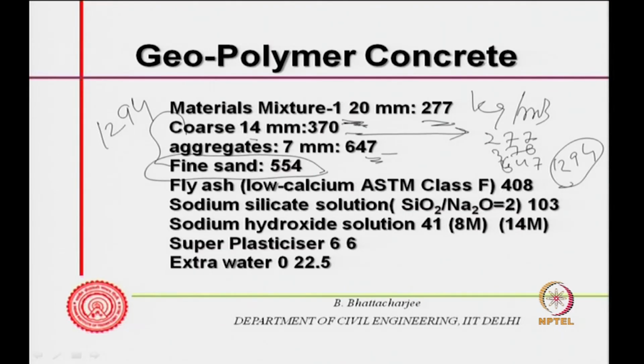Fine aggregate is 554, it is a fine sand. Then use fly ash, low calcium, because this is the binder now. So, this is 408 kg per meter cube, this is the binder, together with sodium silicate and sodium hydroxide, 103 kg, this is 41 kg. So, silicon dioxide to sodium oxide ratio should be equal to 2.